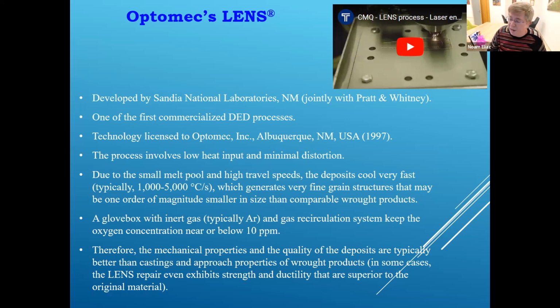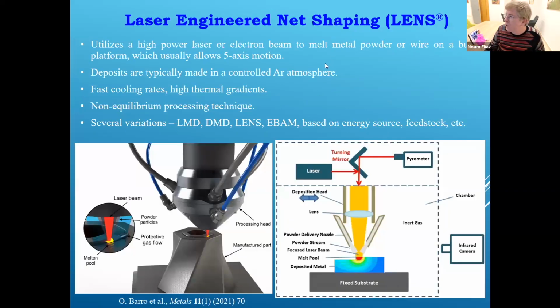Some of the companies, including Optomec, you can buy it with a glove box with inert atmosphere. Optomec allows you to get less than 10 ppm oxygen in the chamber. This is very important when you want to get high quality aluminum or titanium or magnesium parts, as we are using, for instance. Okay, so the process looks like this.